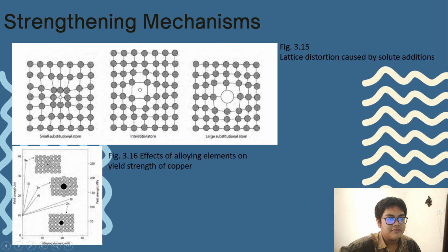And the solid solution strengthening, as we can see in figures 3.14 and 3.15. Figure 3.16 shows that extra stress is required to push the dislocation past the solute atom. The effect of several alloying elements on the yield strength of copper is shown in figure 3.16. Nickel and zinc atoms are about the same size as copper atoms, but beryllium and tin atoms are much different in size from copper atoms. Increase in the atomic size difference and amount of alloying both result in increases in solid solution strengthening. Solid solution strengthening of iron and steel: addition of carbon to pure iron increases room temperature strength by more than 5 times.